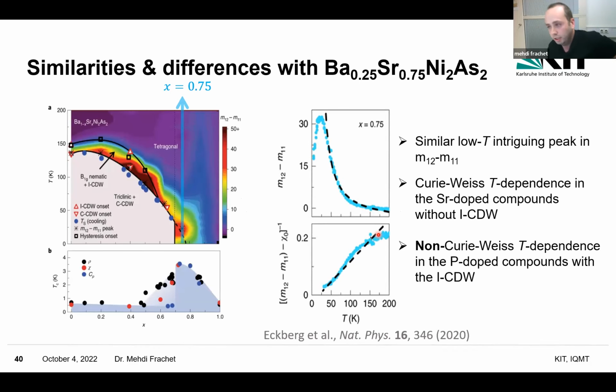The first thing I would like to mention is that this sample is interesting because it has nice similarities and differences with this 75 strontium doped sample, which was studied by Jean-Pierre Paglione and co-workers. The similarity is that in the strontium doped sample, you also have a maximum of elastoresistance close to 25 Kelvin in the absence of a known phase transition. So there is no triclinic phase anymore at this doping in particular. The difference is that in the strontium doped sample, there is this nice Curie-Weiss temperature dependence, which is not observed in the phosphorus doped sample.